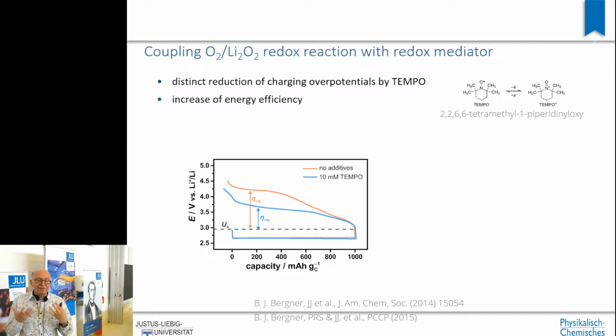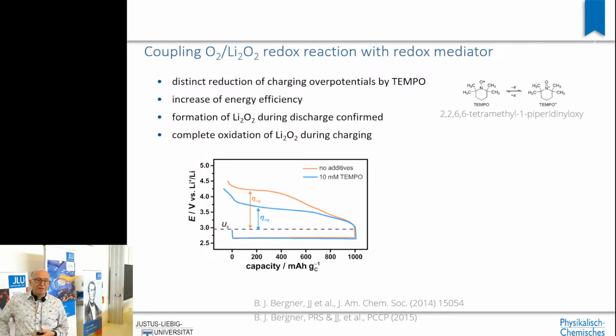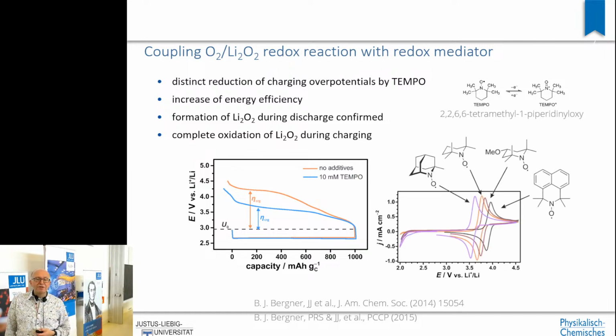reducing this overvoltage and helping to get the electrons back from the peroxide species or from the reduced oxidation species is something where we cooperated with a group in organic chemistry with Peter Schreiner, who's a specialist for small molecules, for functional molecules, in this case for radical molecules, and varying these molecules. I think this is extremely interesting for students in organic chemistry. You can really tune the transfer of electrons to and from the oxygen molecule. I will not go into detail, but that is something where organic chemistry and the redox chemistry that can be used in organic molecules very nicely couples with the inorganic world in batteries.